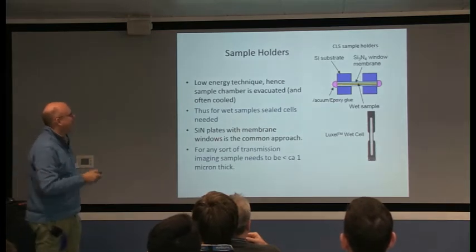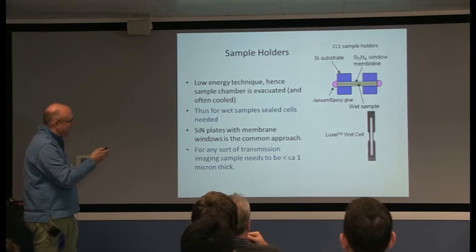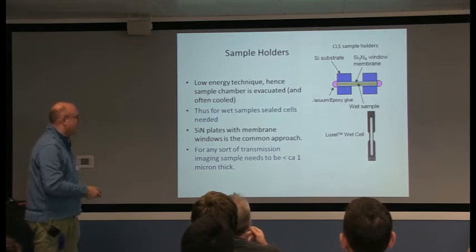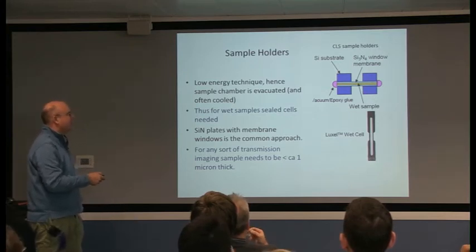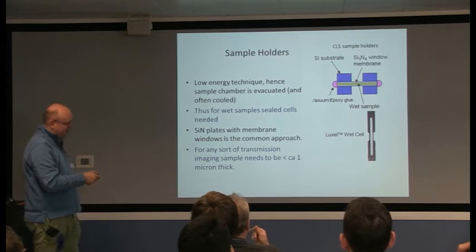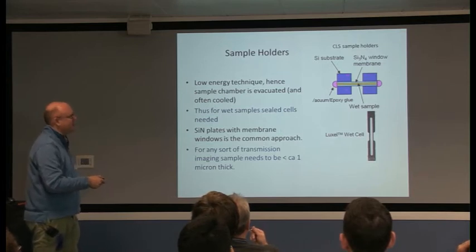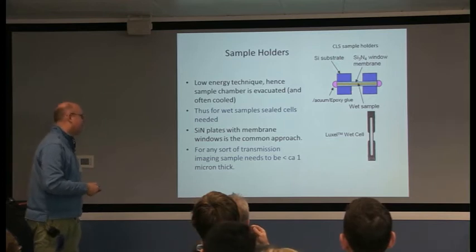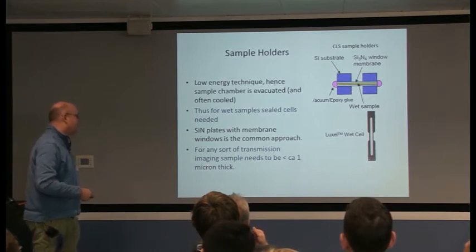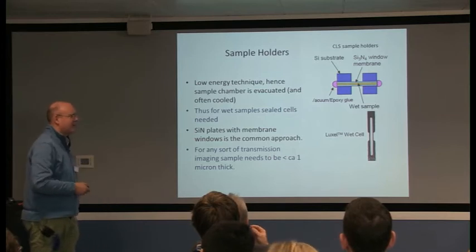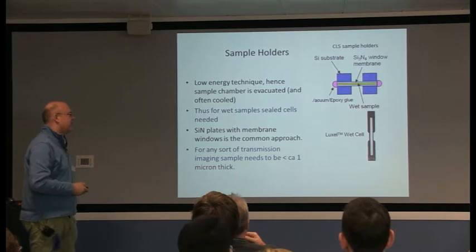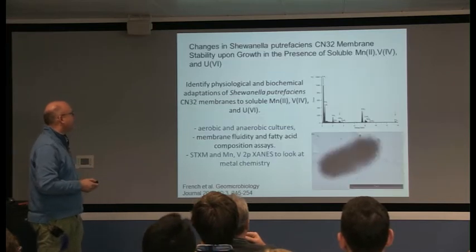Sample holders I mentioned, if you want them for wet cells, there are commercial examples like this Luxel wet cell, or you can make silicon nitride ones. The silicon nitride windows I showed earlier can be glued together, and you can put a wet sample between the two, because you have to seal them since the whole thing is in a vacuum. Your sample can't really be much more than a micron thick for the X-rays to go through at these energies, especially if you're working near the carbon edge, trying to image bacteria.